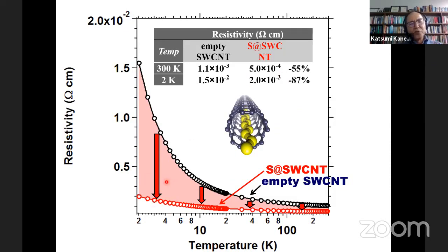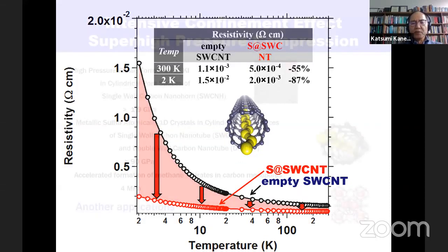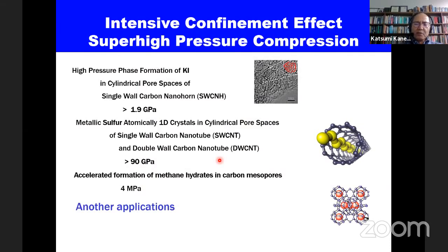This is just powdered-form electrical resistivity, not single rope carbon nanotube data. That's still very difficult. Sulfur included in the single carbon nanotube gives a very low resistivity compared with without sulfur. This indicates sulfur should be metallic, and Raman spectroscopic data also support the metallic property of sulfur. We don't apply 90 gigapascal, just evaporate sulfur in vacuum, but the very unique structure, which is produced under 90 gigapascal, is produced in the single carbon nanotube. So in-pore pressure works for this case.